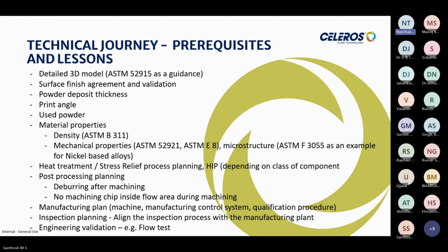In our particular case, we had some issues with post processing. The easiest thing to do is to print the part. If you give a drawing to a supplier, printing the part is very easy, but post processing is the biggest challenge, especially on a component like what we are discussing here, which would have about 1,000 holes like windows around the part. So we had to plan a lot. We did a lot of discussions with the Wipro team, and they were very open. They gave a lot of suggestions, and I think this is an activity that needs a lot of collaboration to be done.